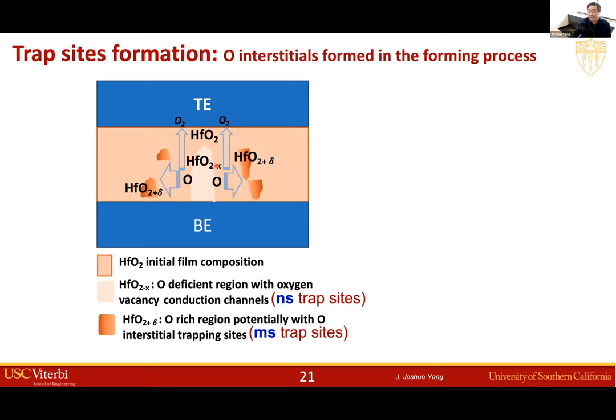And then you need to put oxygen somewhere. Some of the extra oxygen will go out of the device, being released, but this process is so fast, not all the oxygen can go out. Actually, many of them get pushed away to the side and stay inside the dioxide, and the oxygen going here become interstitial. And then inside of the center, you have oxygen vacancies. Both can be electron traps, but oxygen vacancies are a faster trap with nanosecond time scale. It won't affect our electrical operation. And such interstitial trap center can have a millisecond trap lifetime so that it can give us the telegraph noise.